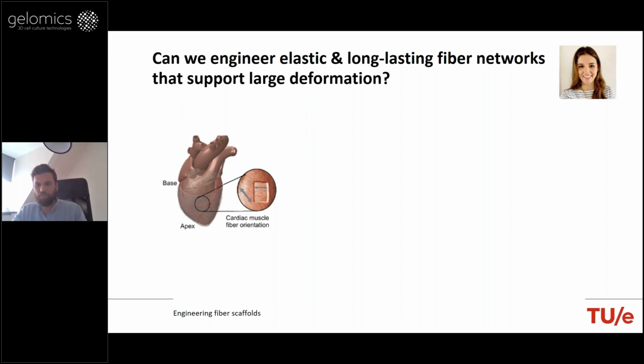electrowriting, which basically suffer from permanent deformation, as I mentioned. The way to go around that was, of course, play with the design in order to get that elastic behavior, but that it's not always desirable because the printing process also has limitations in terms of the accuracy of the geometry that you can print with. So we have been looking at a different class of materials that could allow us more long-lasting fiber network fabrication and to perform in an elastic way under large deformations.